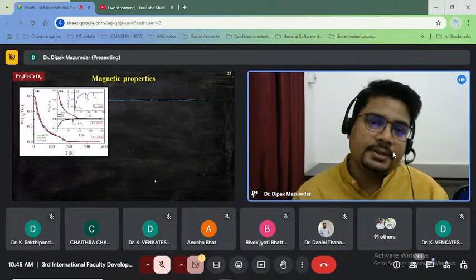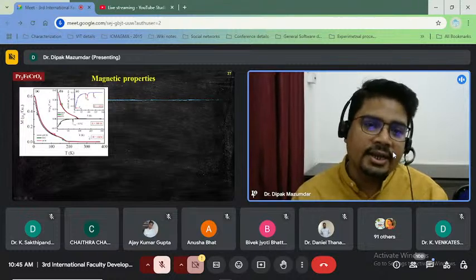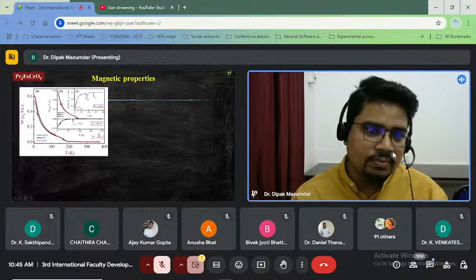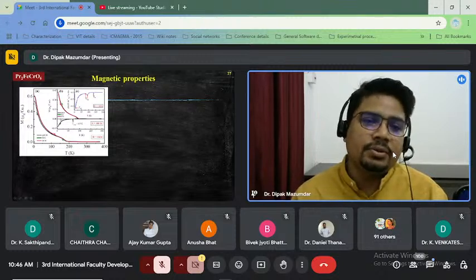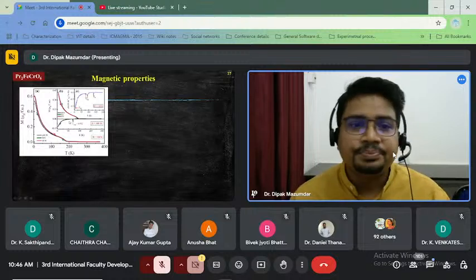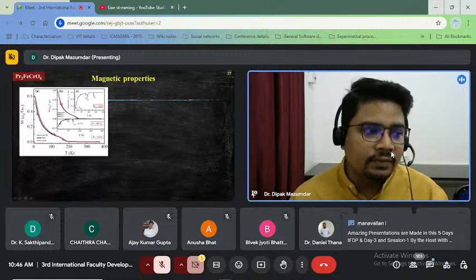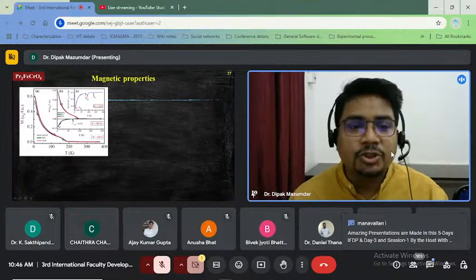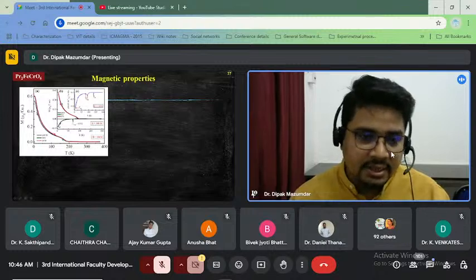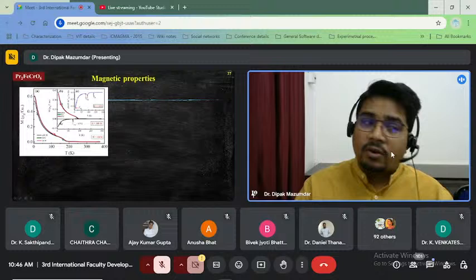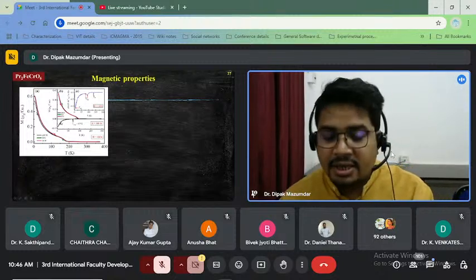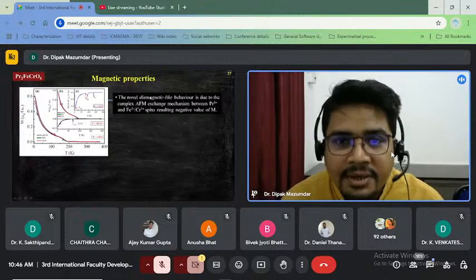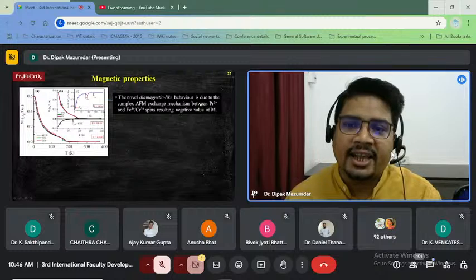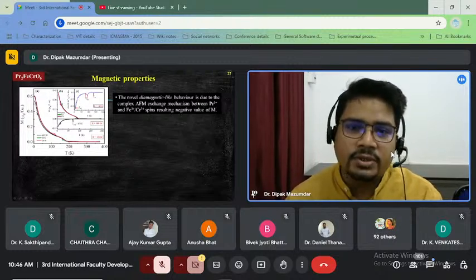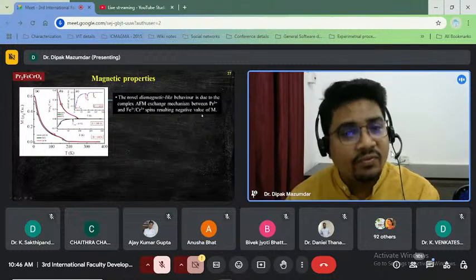Now we come to the magnetic properties. So here you can see magnetization data taken at around 100 oersted and 1 kilo-oersted. First let me discuss the intermediate picture, the 100 oersted data. In this data we can see the virgin curve shows negative magnetization, and this is due to the diamagnetic effect of this compound. Although it's magnetic, it shows diamagnetism-like behavior. This diamagnetic behavior is due to the complex antiferromagnetic exchange mechanism between praseodymium 3+ ions and iron-chromium spins, resulting in a negative value of magnetization.